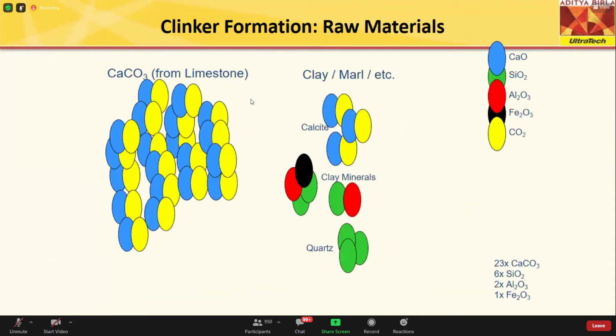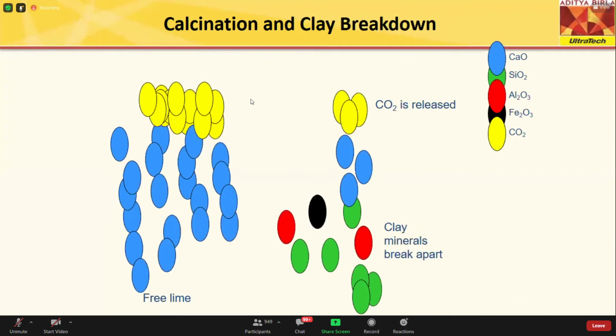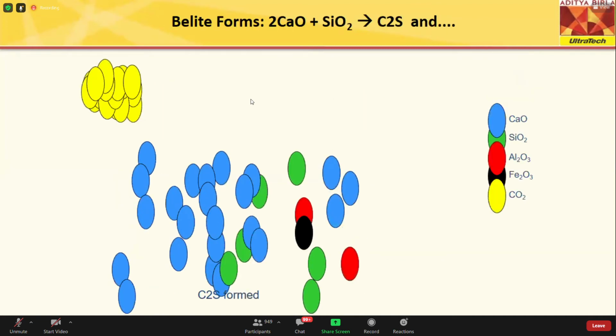Then again, a simplified form for explaining this calcium carbonate when heated. If you see these different colored circles, blue is calcium lime, green is silica, red is alumina, black is iron, and yellow is CO2. As seen at different temperatures, initially this carbon dioxide escapes out, and the main oxides left in the system are lime, silica, alumina, and iron. They participate in reaction to form C2S, C3A, C4AF, and then finally C3S.